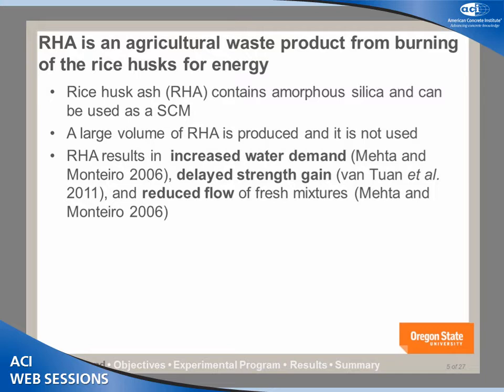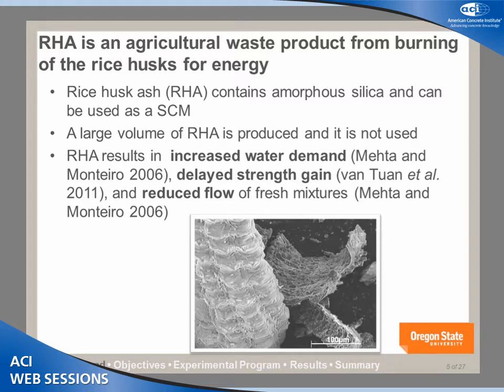Rice husk ash has challenges including high water demand because of its unique structure, delayed strength gain due to the pozzolanic reaction, and reduced workability. This is an SEM picture of the rice husk ash. We can see the outer shell of the rice husk ash, and the inner shell has a mesoporous structure. That's why it captures water and reduces workability.